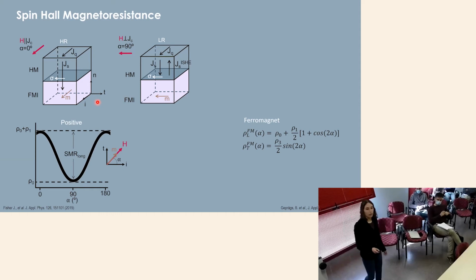So if we now start measuring the resistance in the metal with the magnetization of the ferromagnetic layer rotating, we can have a dependence of the resistance on the angle at which the magnetization is pointing. And this is quite well known from a theoretical point of view, and the observed result is a modulation of the resistance that goes with the double of the angle alpha of the magnetic field. Now, all of this works for longitudinal resistance, as I was saying, but actually we have a modulation also when we measure in transverse geometry, and this will have a 45-degree shift with respect to the longitudinal one.